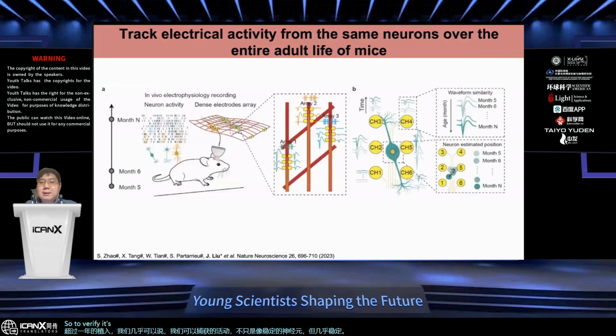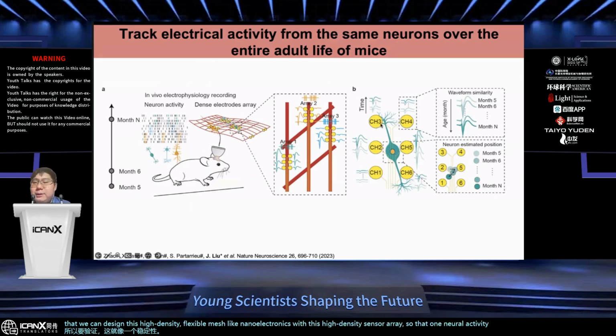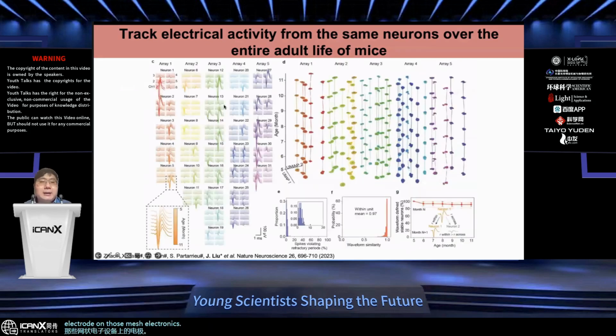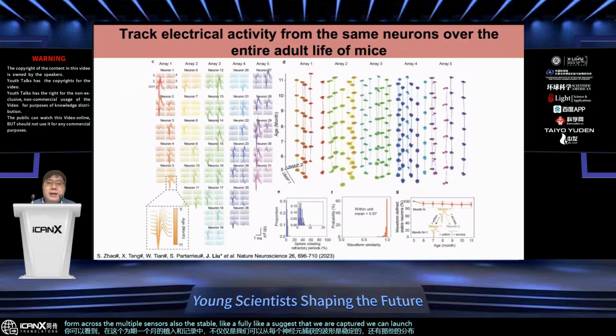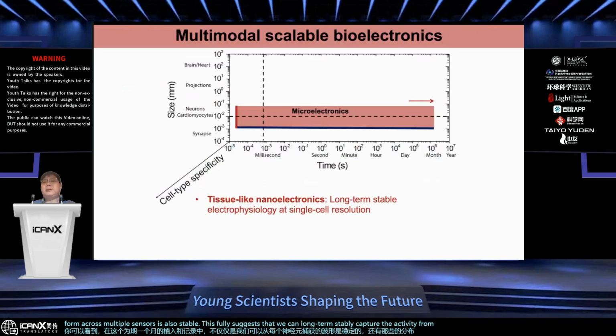To verify the stability, we can design this high-density flexible mesh nanoelectronics with a high-density sensor array, so that one neuron's activity can be simultaneously captured by multiple electrodes on the mesh electronics. You can see that over this month-long implantation and recording, it's not just the waveform captured from each neuron that is stable, but also the distribution of those waveforms across the multiple sensors is also stable. This fully suggests that we can stably capture the activity from the same neurons long-term by using those flexible electronics.